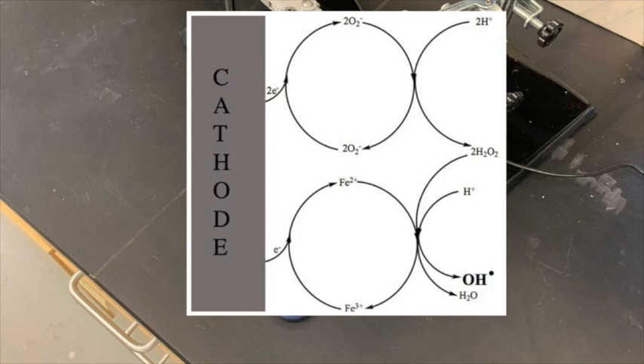This hydroxide radical can attack the edge or defect sites of our existing nanosheet or quantum dot solution. Through doing so, it will break the existing nanosheet or quantum dots into smaller and smaller pieces. This allows us to control the size of our quantum dots by changing the amount of time that the solution is exposed to the electro-Fenton reaction.